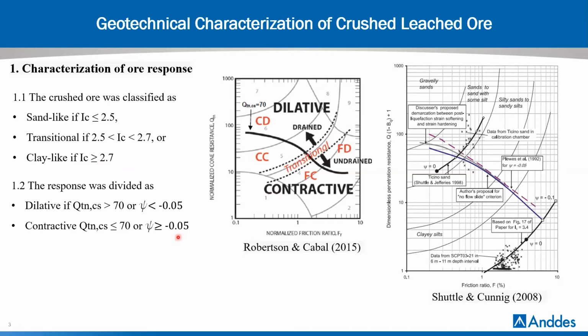With the results of the CPTs, areas with dilative or contractive behavior have been identified. This identification was used to locate areas likely to experience strain softening. To define whether the behavior of the crushed ore is contractive or dilative, the approaches proposed by Robertson and Cabal 2015 and Shuttle and Cunning 2008 were adopted. Robertson and Cabal employs the clean sand equivalent normalized cone resistance Qtn,cs, where the limit between contractive and dilative response is Qtn,cs equal to 70. The approach of Shuttle and Cunning 2008 employs the state parameter, with the contractive-dilative threshold located at minus 0.05.